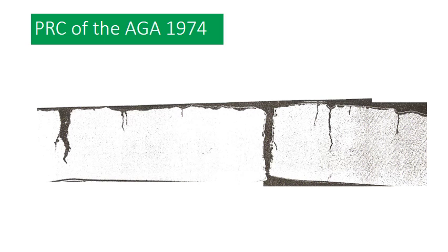And if you dig through those symposium notes, you find this quite fantastic micrograph of a cross-section through a failed pipe, which has got some stress corrosion cracking in it. And it is not exactly perfect, but I think you can sort of see that there's a 3-to-1 spacing ratio there. What I've done to just make it a little bit clearer is I've added a few annotations here.